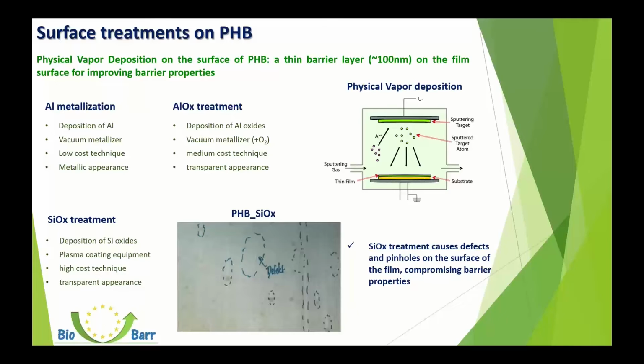Another technique to obtain a transparent barrier layer is the SiOx treatment, that consists in the deposition of a thin layer of silicon oxides by a plasma coating equipment. That is a technique with a higher cost compared to conventional metallization and also AlOx treatment.